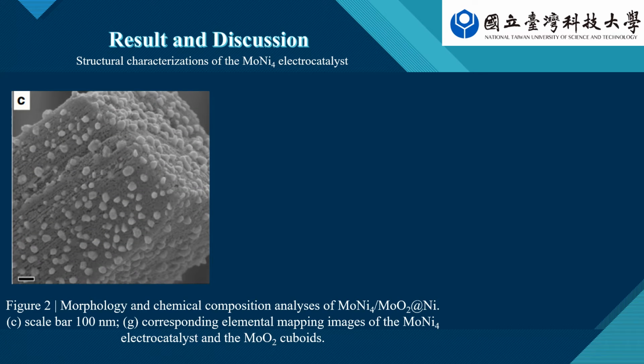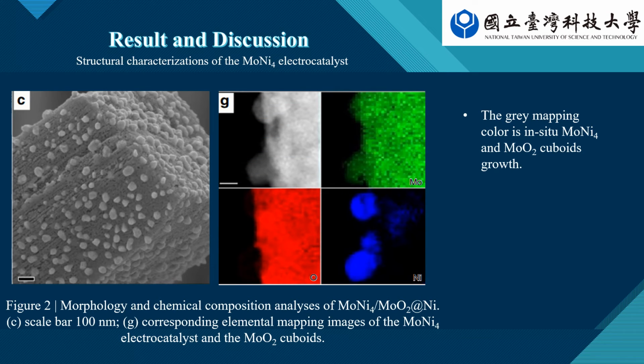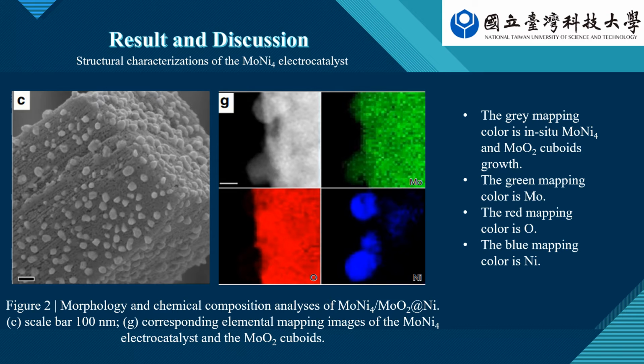Based on figure 2C, this is the sample calcined at 500 degrees Celsius for 2 hours. The outer part of the cuboids undergoes a phase change and forms the nickel molybdenum oxide phase, where the nickel becomes transferred into dots while MoO2 covers the cuboids. It can be confirmed via X-ray elemental mapping as shown in figure 2G. We can see the gray mapping color is in situ MoNi4 and MoO2 cuboids growth, the green mapping color is molybdenum, the red mapping color is oxygen, and the blue mapping color is nickel.